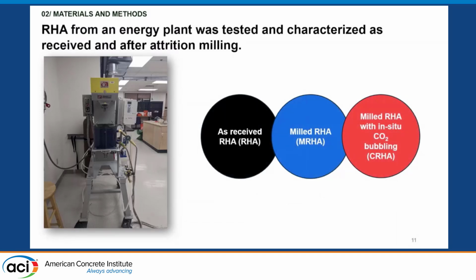And so the kind of categories that I have here is as received rice hull ash, so the rice hull ash from the energy plant, the attrition milled, which I'll be referring to as MRHA, and then also I did work with some milled RHA with in situ CO2 bubbling, which is another feature that we have on our attrition mill, is the ability to flow different gases into the mill while it's running.